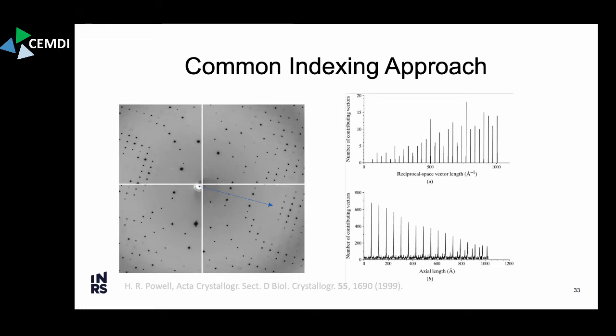Lots of spots going to high resolution, well defined. If you just take the dot product of each spot with this vector along here and histogram it, you get a distribution like this. And if you take the Fourier transform of that, then what you have are regular peaks. This regularity allows you to back out the unit cell constants. And so then you can identify the orientation of which planes these peaks correspond to based on this Fourier transform